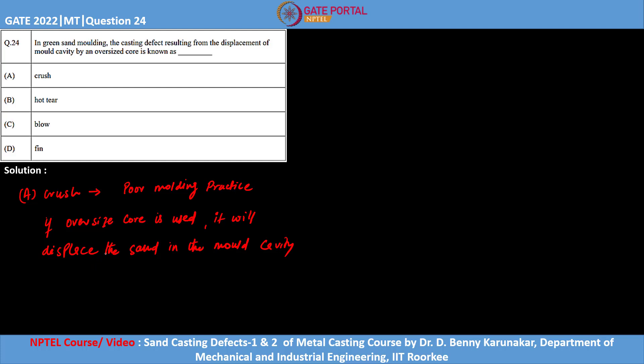Another reason is careless closing of the mold - if you carelessly close the mold, the sand in the mold cavity will be displaced, leading to a crush defect. Other reasons include improper alignment of flask equipment, uneven flask joint, bad fitting jackets, or bad bottom board. All these types of mishandling lead to unequal pressure on the mold, which finally results in displacement of sand in the mold cavity.